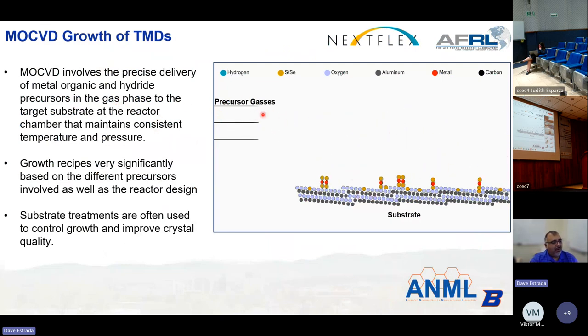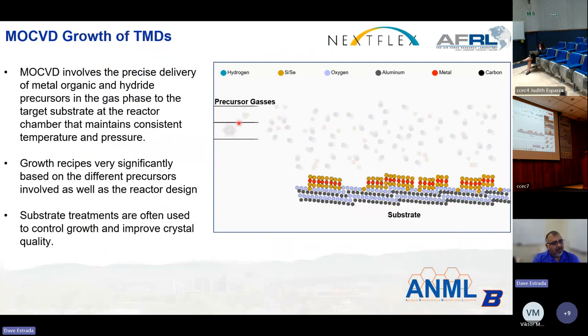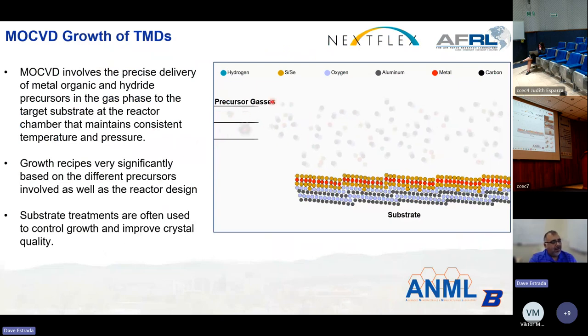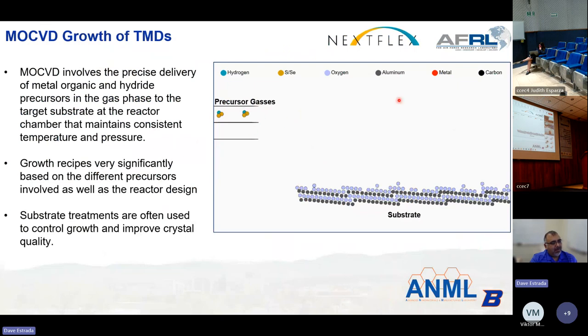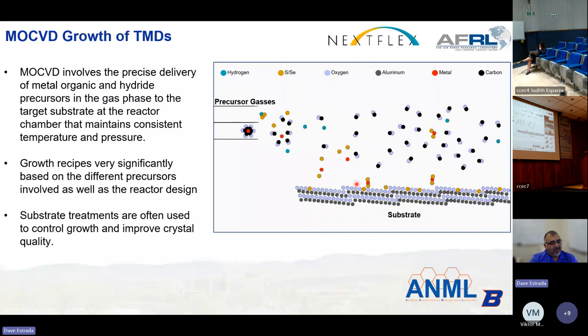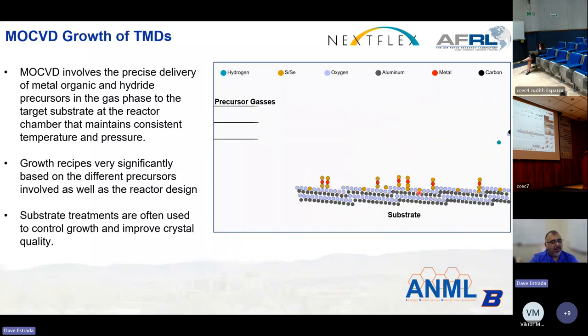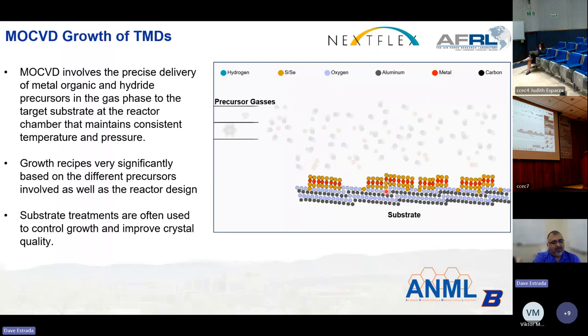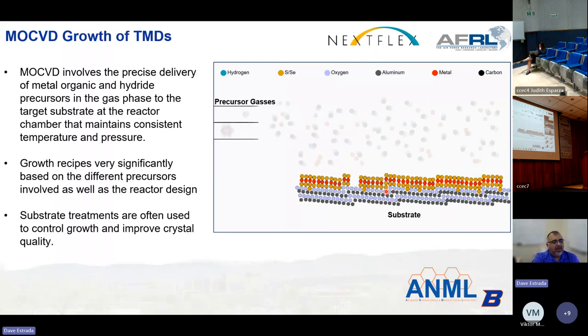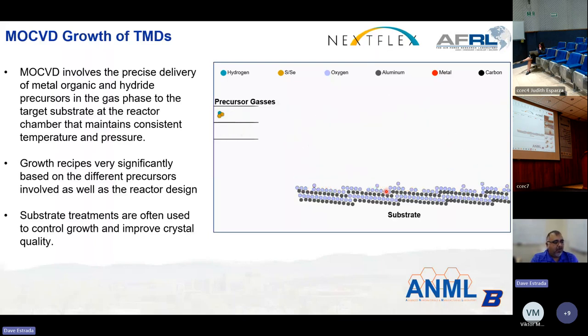So this little cartoon here shows that by controlling the precursor gases, we can insert our transition metal containing precursor. So we're using molybdenum carbonyl, tungsten carbonyl, and then we mix that with hydrogen sulfide, right? And so that can help start the nucleation on the substrate, and over time, that nuclei will grow until you have a coalesced film, right? There's a lot of substrate treatments that go into this. We have to control temperature, pressure, gas flows, a lot of process parameters to optimize this growth.